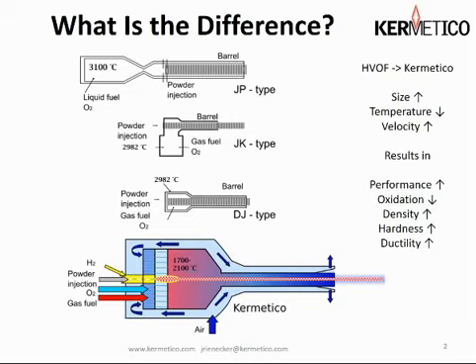Coating density is extremely high because of the high velocity of the spray stream. Hardness is high for the same reason, and we maintain ductility because we're not dissolving oxygen into the metal matrix, as that tends to make coatings brittle, and solid particles absorb oxygen at a rate about 1,000 times less than liquid particles.